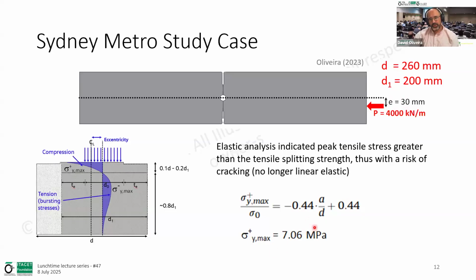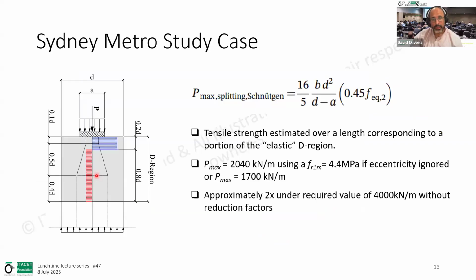So using that typical approach, we estimated peak bursting stress in the order of 7 MPa, which we identified was exceeding our tensile design capacity. Therefore, we would be going beyond the elastic limit into the cracking zone. And that's where the guidelines stop working, because the only recommendation that we have up to this point is linear elastic, or if we start introducing conventional reinforcement, which is something that we didn't want to do. So now we started investigating. At that time, this was circa 2021, maybe going to 2022.